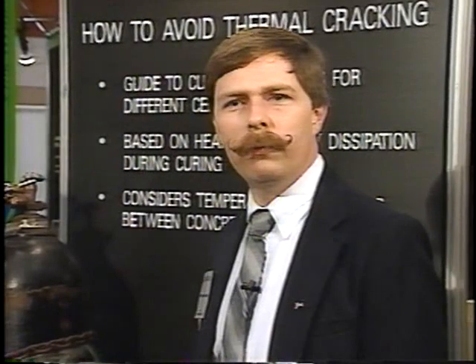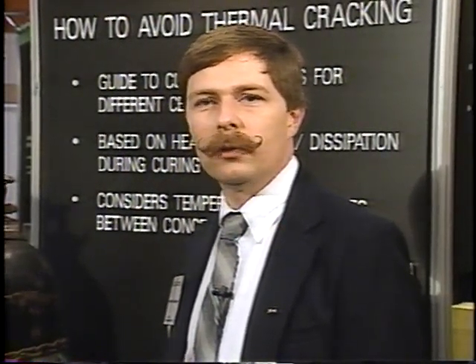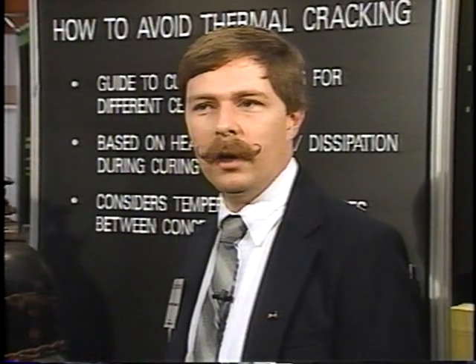We've tested a little over 20 aggregates so far. We've got no false positives. That means that none of the aggregates that have passed our test have had any cracking problems in the field. We've had one false negative. An aggregate failed our test, but it was still a good aggregate.